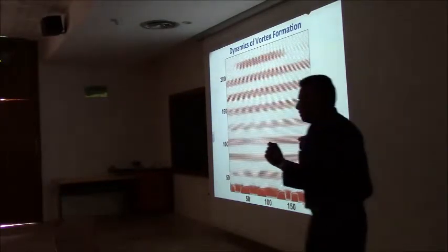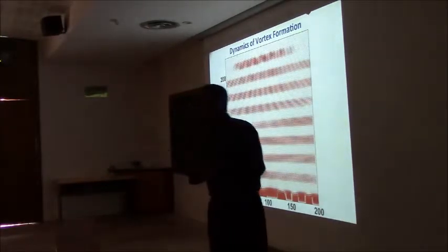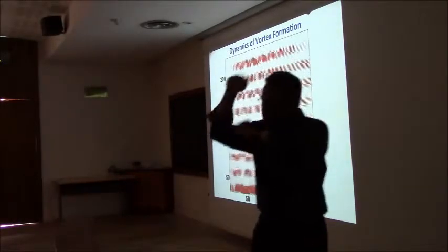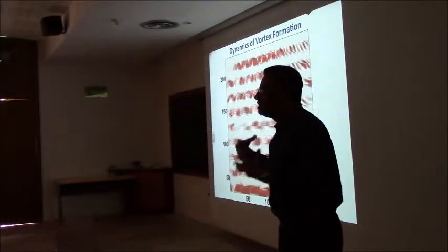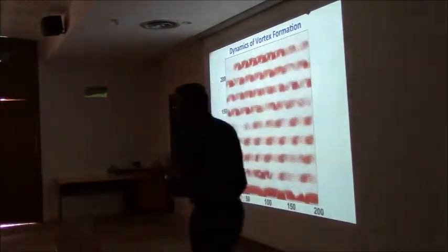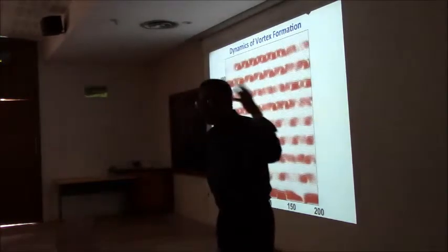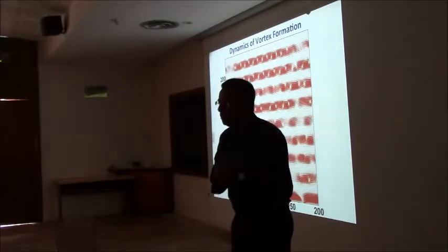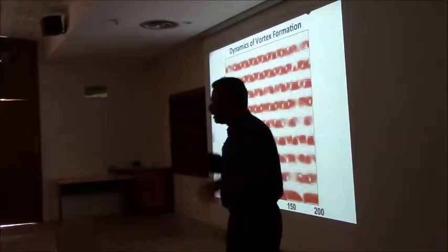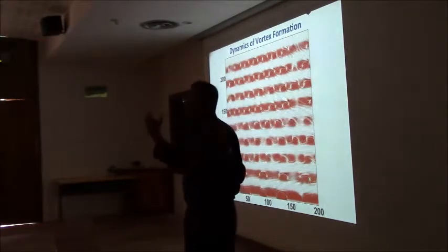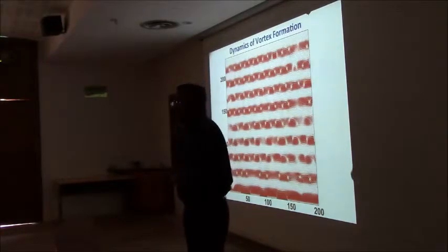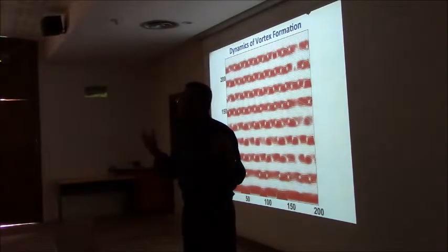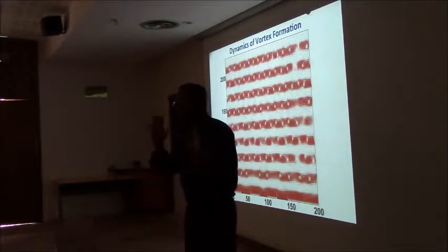So the question that we were asking is, about 25 years ago, there were people who predicted that in superlattices, you should start to see a change in behavior from a particle, which is typically how people think of phonons, to coherent transport behavior, where it behaves like a wave. That approximately happens near the mean free path for phonons. And for these oxides, the mean free path is about 3 to 4 unit cells, maybe 5 unit cells.